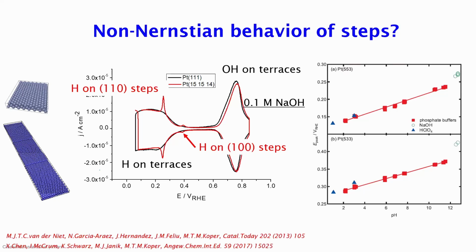It can also explain, and that's a little bit more of an evolved argumentation, why the peak is sharp, because we're replacing an adsorbate that is small by an adsorbate that is big, and that can lead to effectively attractive interactions. It does not explain why we have this pH dependence, but then I argue this pH dependence is only apparent because as we change pH, we typically also change cation concentration. It's very difficult to change pH without changing cation concentration.